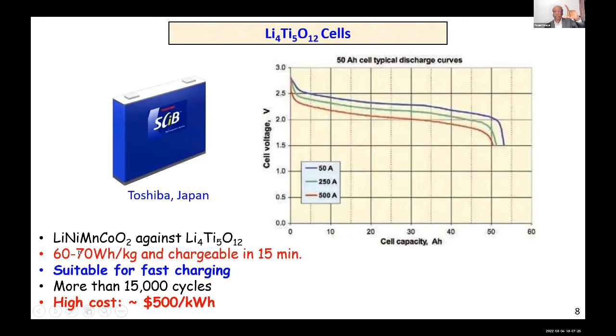LFP graphite in 18650, you can take somewhere about 100 to 105 watt-hour per kg, and the cost is about $100 to $125 per kilowatt-hour. Whereas here, this is about $500 per kilowatt-hour. So any technology you take, NMC versus LTO or LFP versus LTO, the cost is pretty high, $500 per kilowatt-hour. It is safe. It helps you with quick charging, quick discharging. Unfortunately, it is at least 5 times higher than LFP versus graphite.